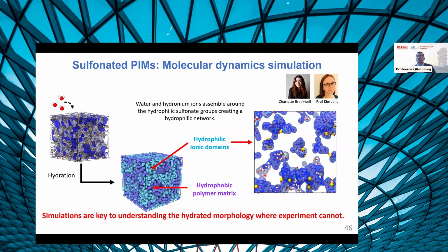So we did some molecular simulation to understand the mechanism, because initially PIM-1 was hydrophobic and some of the PIM-SBF was also hydrophobic. But after modification, they become hydrophilic. And once this polymer absorbs the electrolyte, they form this kind of hydrophilic ionic domain. So the size and the distribution of these water clusters are critical to determine the ion transport.